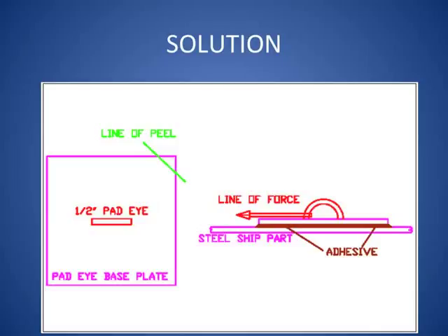Well, that's a good question. I think what I usually find as a criteria for creep, if you load something like adhesive or viscoelastic material to about 80% of its breaking strength, then you've got to worry about creep. But I thought I was being reasonably conservative here, using a safety factor of 4. So I'm only loading it to 25% of its ultimate strength. I wouldn't worry about creep in that application. We're not even getting close to it. You could probably test it then the same way that you would test any other pad eye, a short duration test. And if you've got a pad eye holding a load at 25%, and we're worried about creep at that very low stress, I would say you need to speed up your shipbuilding operation a little bit. It's hung there too long.